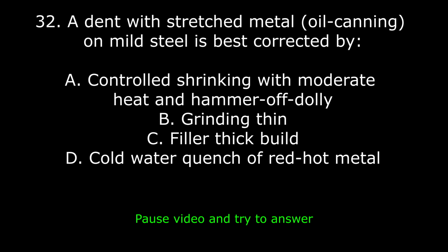32. A dent with stretched metal, oil canning, on mild steel is best corrected by: A. Controlled shrinking with moderate heat and hammer-off dolly. B. Grinding thin. C. Filler thick build. D. Cold water quench of red-hot metal. Answer: A. Controlled shrinking with moderate heat and hammer-off dolly. Explanation: tightens overstretched areas carefully.